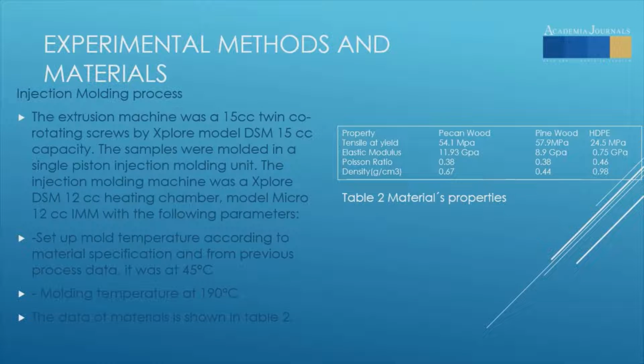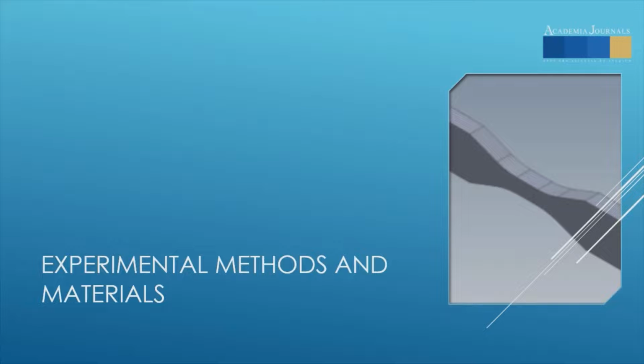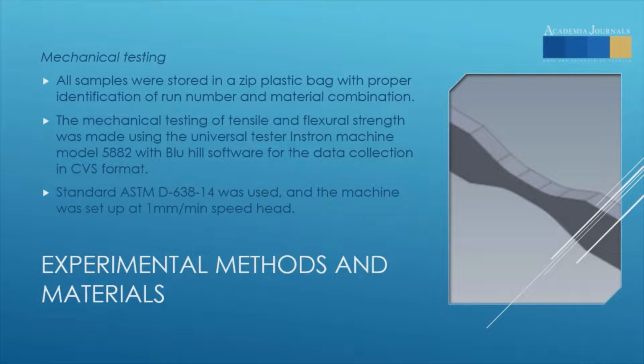The last process was injection molding, using a twin screw extruder for mixing and an injection molding machine with a small piston using the setup mentioned. The material properties are in table 2. Mechanical testing for tensile strength was based on a universal tester machine, an Instron 5882. The standard used for tensile strength was ASTM D638-14.